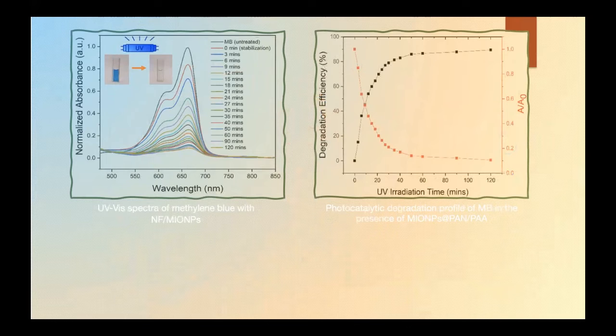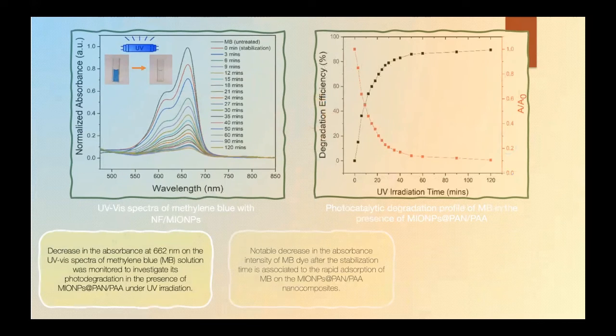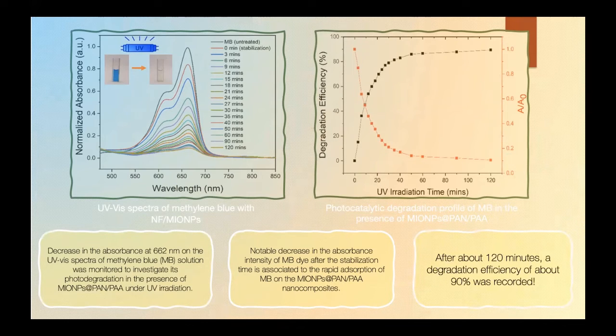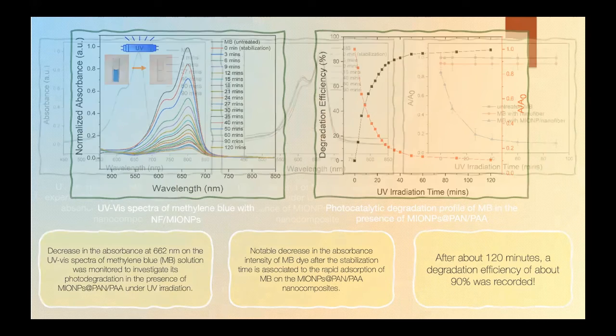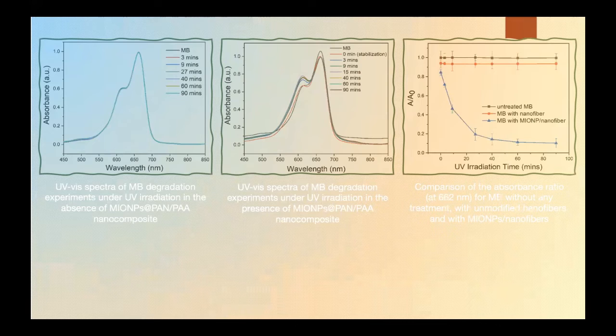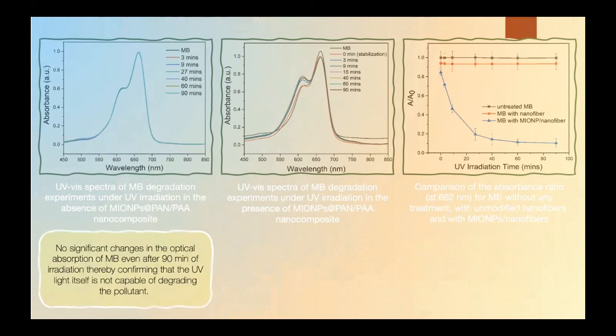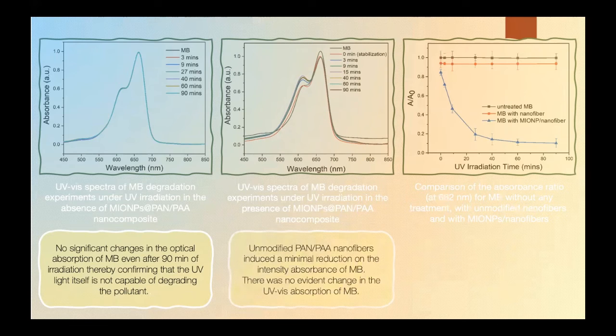Dye degradation experiment revealed a notable decrease in the absorbance intensity of the dye after some stabilization time, which is associated to the rapid adsorption of the dye on the composite. After about 120 minutes, the maximum dye degradation efficiency was recorded with a value of about 90%. Photodegradation of the dye using unmodified nanofibers under UV irradiation exhibited no significant reduction on the absorbance intensity of the dye.